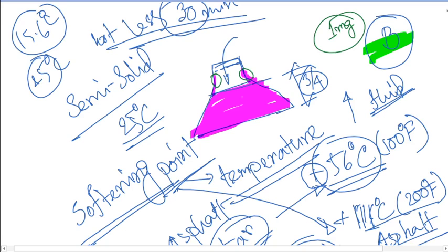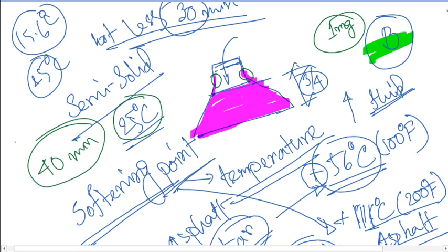After pouring up to 3/4 of the volume, we need to get the temperature to 25 degrees centigrade again. What should we do for that? The same thing: we need to cool it to ambient temperature, which will take not less than 40 minutes. So for 40 minutes you will be cooling this down.